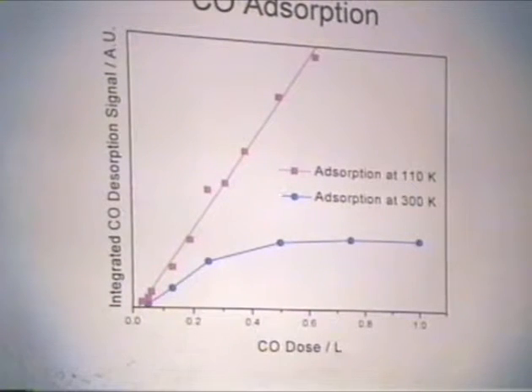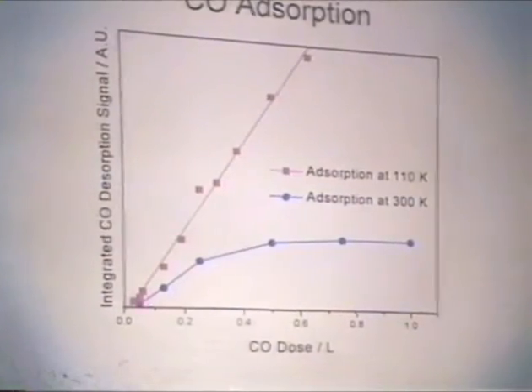Now, if you look at the adsorption at 300 Kelvin, we believe there are 2 regimes. The first one across these 3 points, which has a slope approximated by this very shaky hand, and the second slope across the last 3 data points, a very low slope, indicating, of course, saturation. And so we believe that even in the case of the 300 Kelvin data, we have precursor-mediated adsorption, although since it's populating 1 state, it's across a much smaller dose.